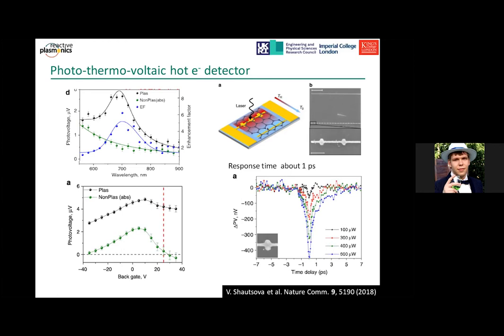We observe the photovoltaic response, which obviously doesn't have plasmonic enhancement, and at the same time shows a non-monotonous dependence as a function of gate voltage, which vanishes at the condition corresponding to the flat band condition in graphene, as is expected for this kind of effect. However, everything changes if we illuminate our plasmonic contact. In this case, we first of all observe the plasmonic enhancement of the effect, and secondly, the whole curve on the bottom here got shifted upwards and no longer crosses zero, showing that there is an additional contribution which we don't take into account normally.